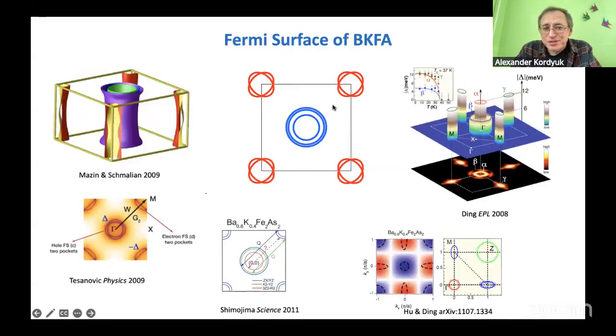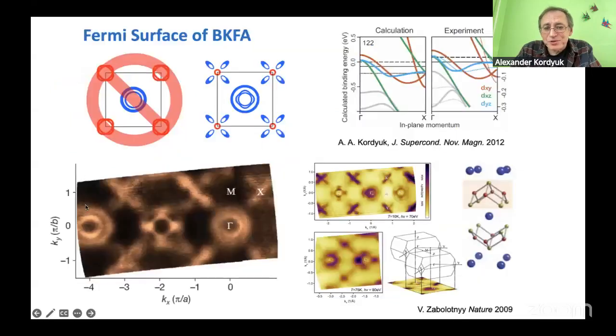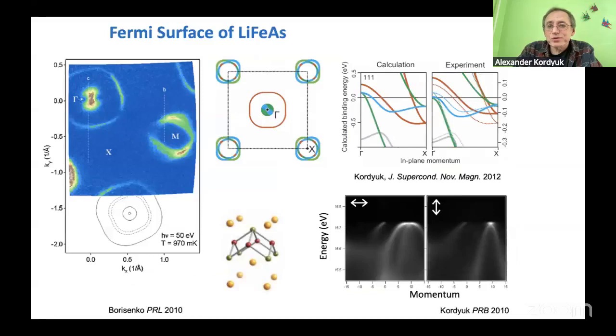They look like this. It was how predicted, and that was our first paper about it, when we showed that it is not like this but like this. Then we believed that it is the consequence of ordering, magnetic ordering, but later we found that it is not. It is really such electronic structure. It is just shifted sufficiently, essentially shifted comparing to band structure calculation, but nevertheless it is the electronic structure of these compounds.